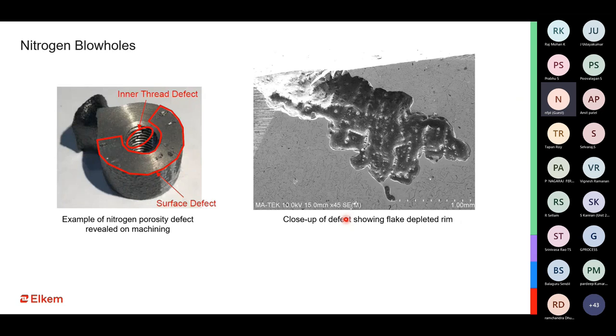So if you look at it, you have some of the defects on the surface and then some of the nitrogen fissures continuing all the way inside, up to about 20-30 mm from the surface of the casting. So you can have nitrogen porosity or this nitrogen fissure kind of defect way inside the casting, which could be a continuation from the surface. When we section, machine or drill a casting, there is a strong possibility of this nitrogen fissure defect being more visible.